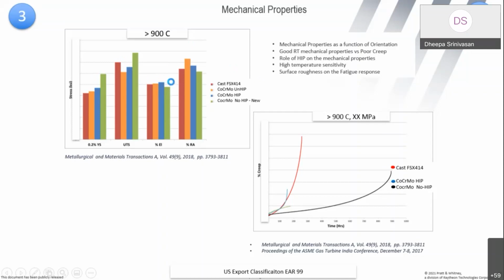However, is it a cause for concern? Maybe it may not be. Why it may not be? Because the fine grain structure that we've got because of the heat treatment can lead to very bad creep response. So immediately we evaluated creep, and luckily for us, the black colored curve, which is nothing but no-HIP cobalt chromoly, the material that we have optimized, is a very slow creeper. Whereas for all the other alloys and all the other systems, every single mechanical property at temperature has to be evaluated.